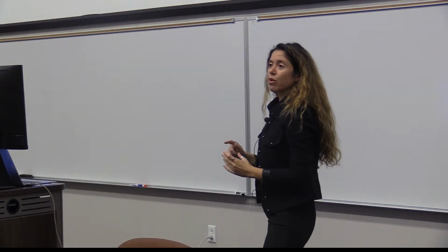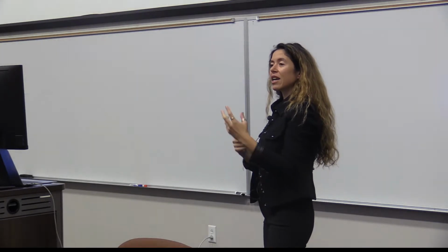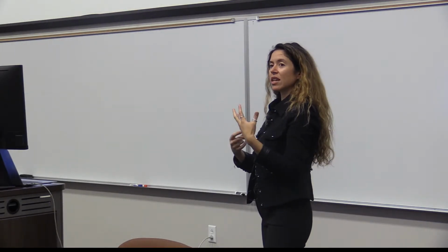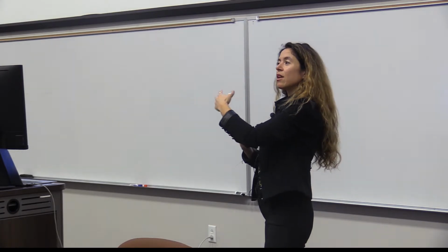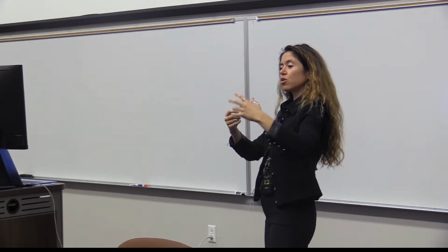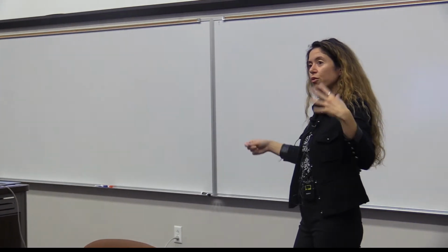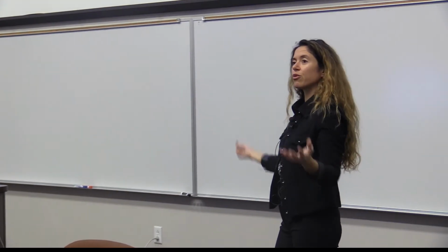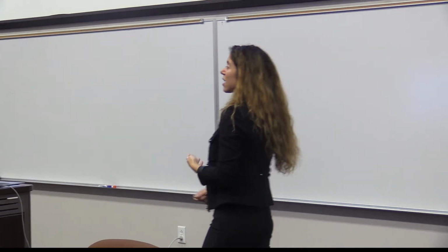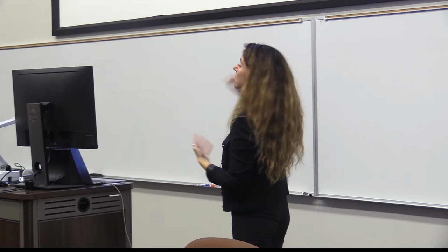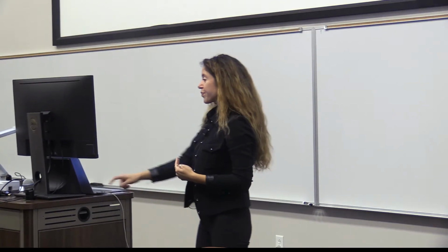That might be counterintuitive, why you would say the Writhe is increasing for less entangled, because the Writhe is a measure of self-entanglement of the chains, and in this case, when the chains have more space, we started from straight conformations, but then when they have more time to diffuse, they go to random coil configurations, and the highest Writhe that we see up there is that of a random coil. So the first ones are tied together, and they can't attain random configurations.